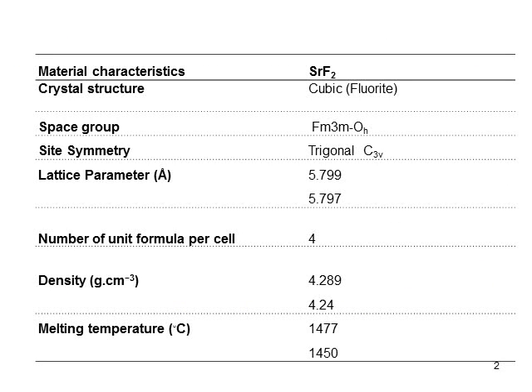The studied matrix is a single crystal of strontium fluoride doped with thulium ions with a molecular concentration of 2%. We have put together in this slide the main characteristics of this host matrix. It has a cubic structure of fluoride type having a cell parameter of 5.8 angstrom. The cell has 4 formula units, that is to say 4 strontium ions and 8 fluorine.